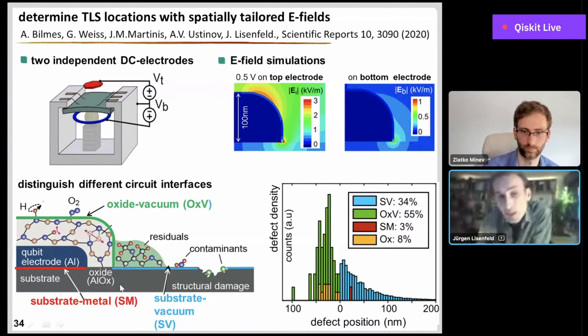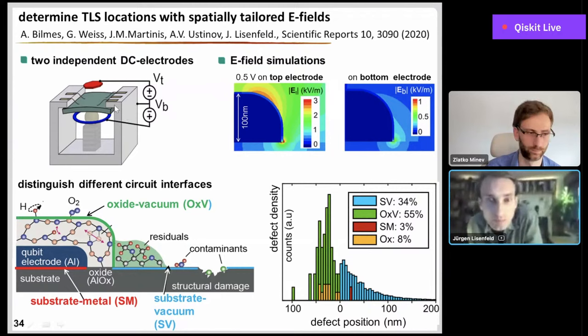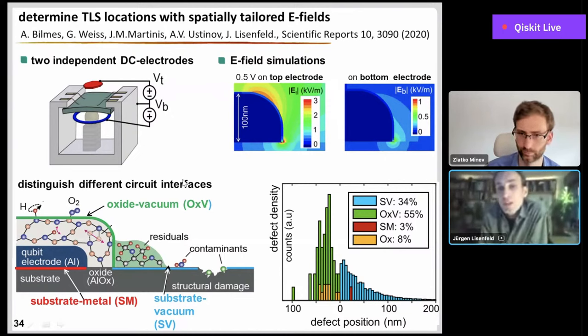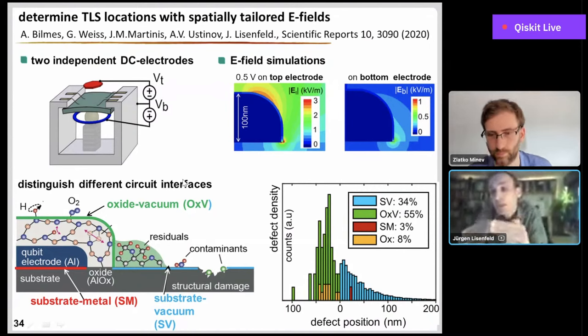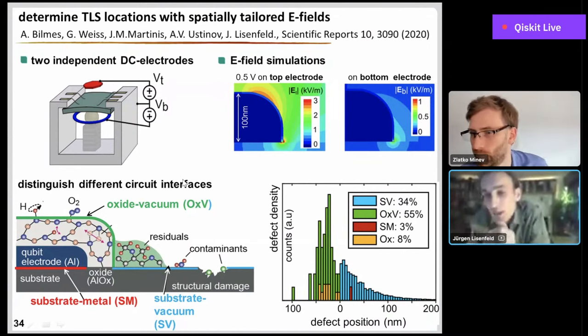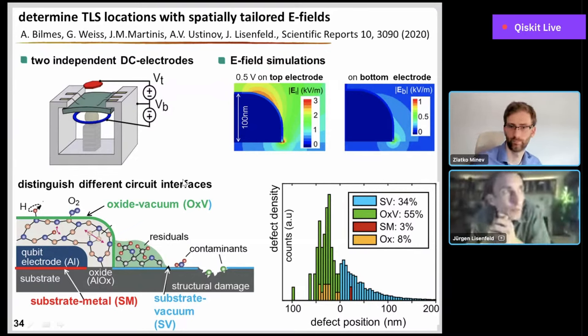Then you could still, of course, use this technique and try to test whether everything worked as expected. And of course, you can also try to not only measure the position of these electrodes along this edge, for example, you could also try lateral electrodes and maybe even produce complete two-dimensional maps of these defects. And then this would nicely tell you, for example, whether you have any corners of your design where maybe you cannot dissolve so nicely the photoresist, whether these are a problem. And I guess things like that could still be nicely studied with this technique.